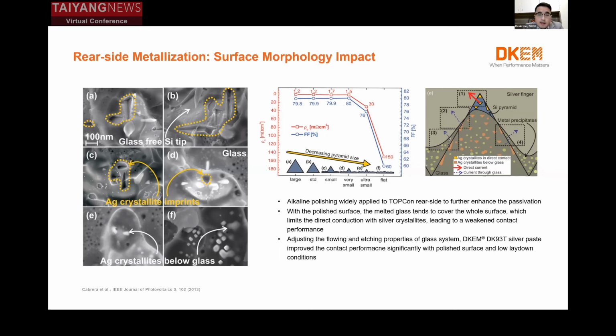And for DKEM, we can do a lot of things to modify our paste. We can adjust the flowing and etching properties of our glass systems. With this kind of effort, DK93T silver paste improves the contact performance significantly with a polished surface, even with low laydown conditions.